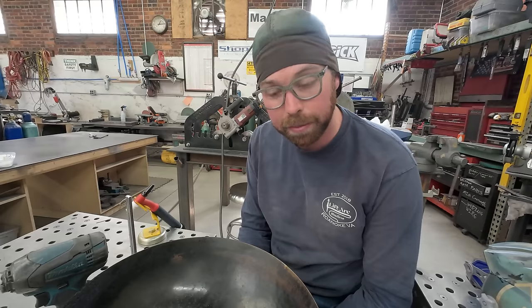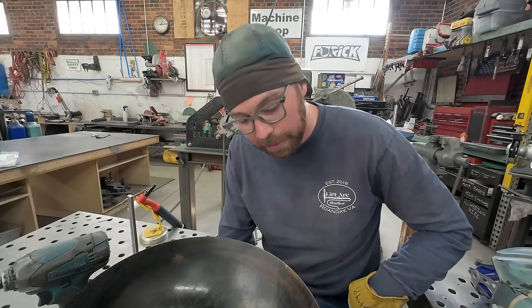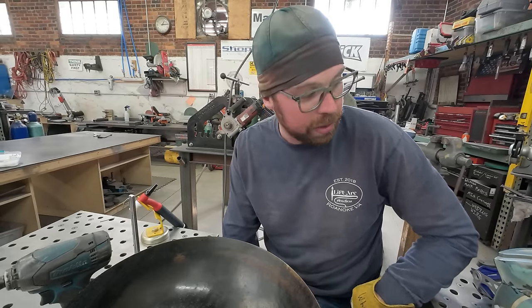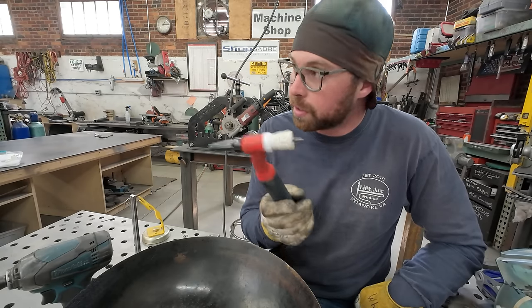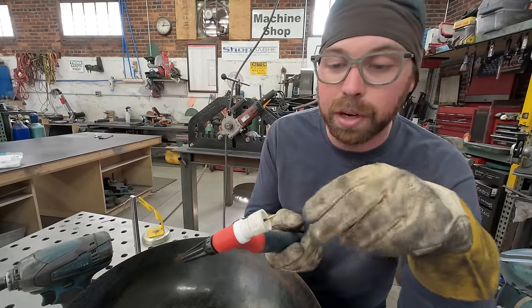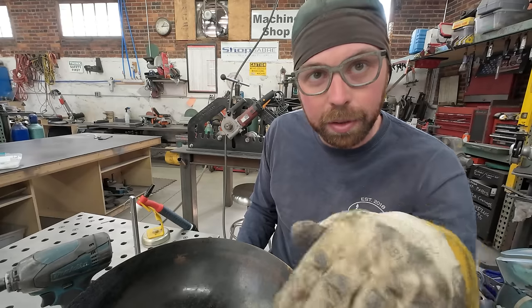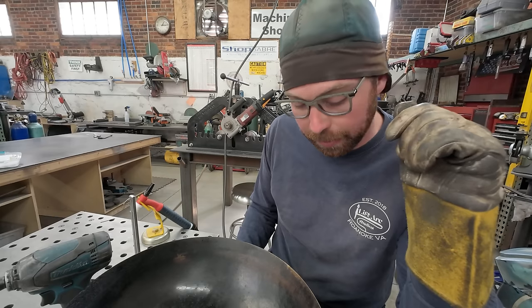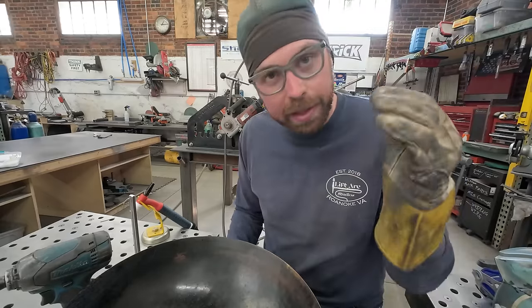They are magnetic, so they're not stainless, at least not completely. There's some surface rust on some of these because they've been sitting for a while, so it's definitely not stainless. I used ER70S-2, 1/16th inch filler rod. I was using the HTP Invertig torch with a foot pedal, 3/32nds electrode sharpened to a point. I set the ceiling at about 80-85 amps and the floor at about 10 amps so it could be nice and gentle. This machine goes down to like two or three amps - start low, establish that puddle quick, and just move up the crack, layering as necessary.